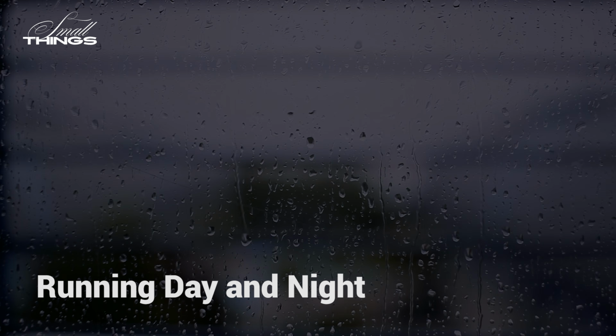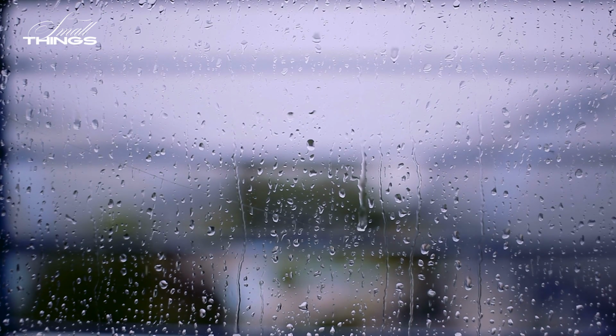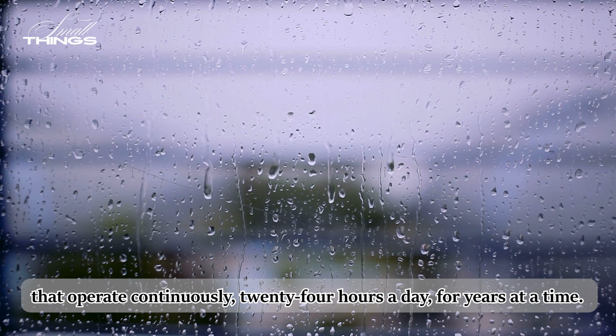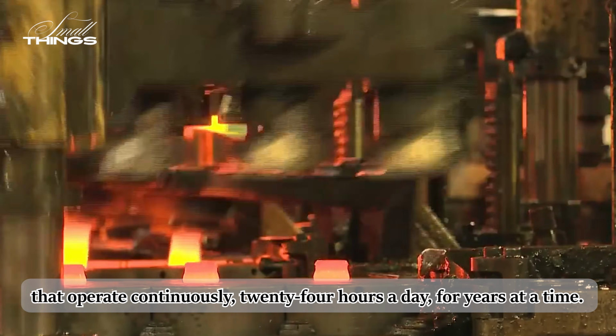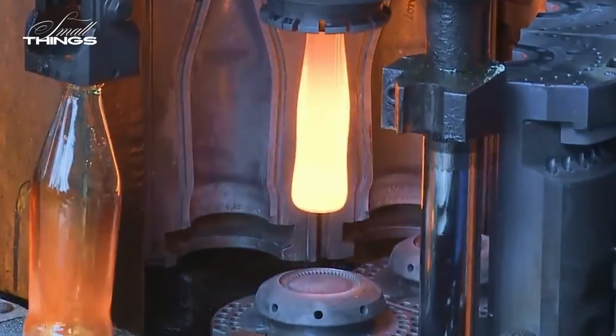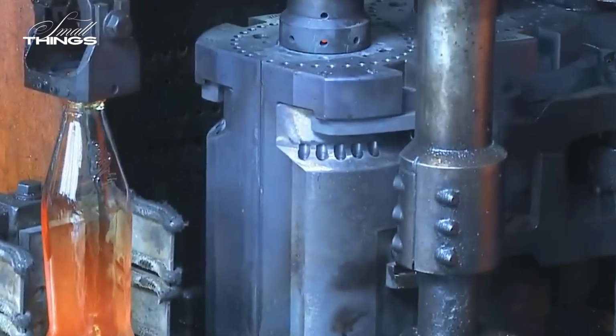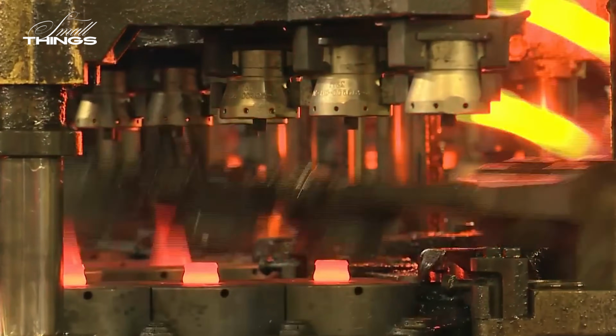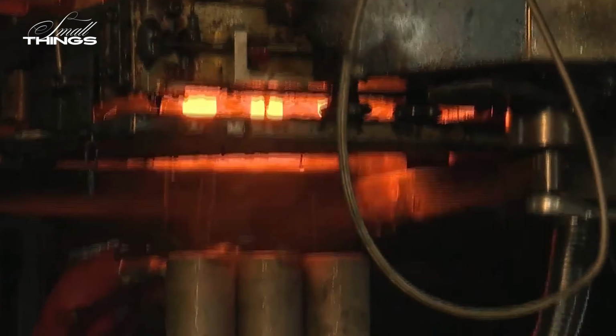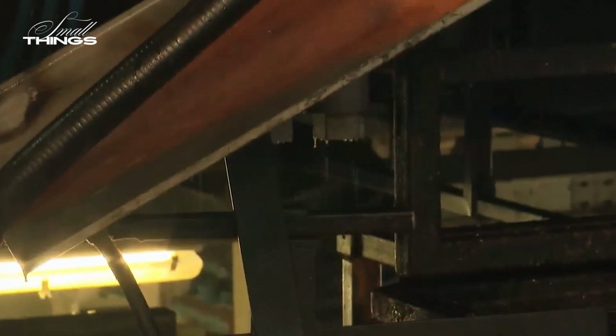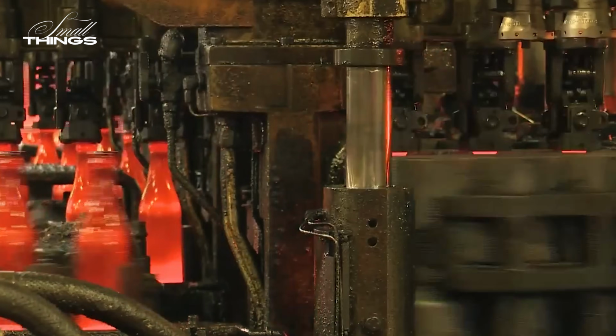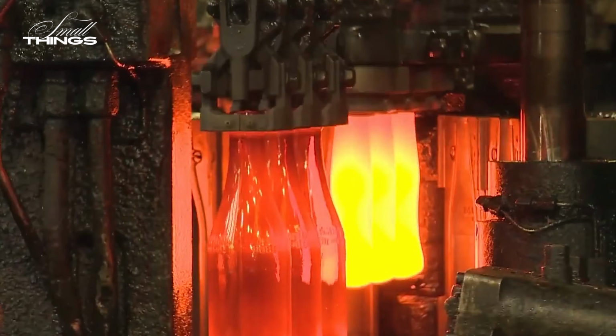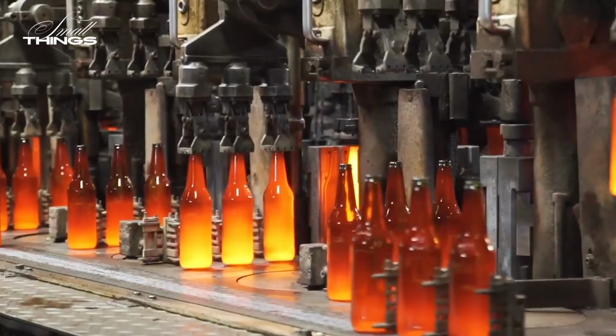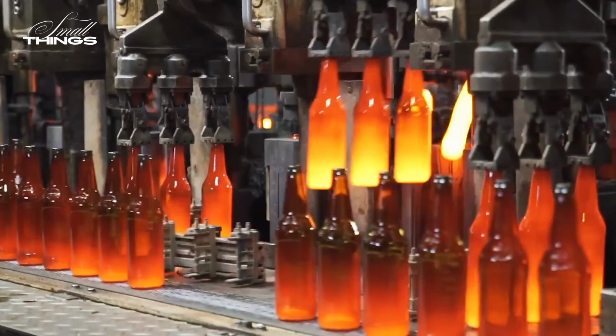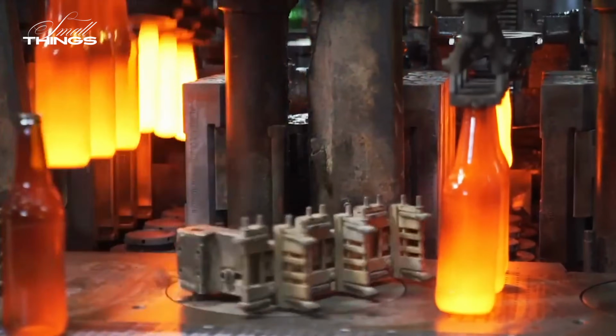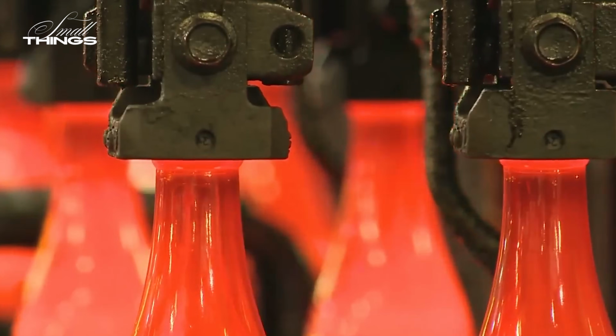Running day and night today, you will find glass furnaces that operate continuously, 24 hours a day, for years at a time. Furnaces are not turned off between production runs because the thermal stress of cooling and reheating a large furnace would eventually destroy its refractory lining. A modern flat glass furnace may run for 10 to 15 years before it is shut down for rebuilding. The economics of glass production are built around this continuity.